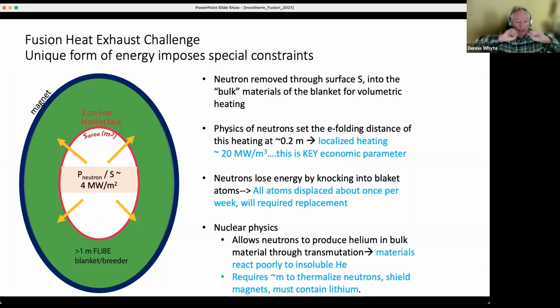So the neutrons basically stream out essentially isotropically out into some large thing. The neutrons move through that surface area S into this bulk. And the physics of neutrons, because they have no charge, set the e-folding distance of this heating at approximately 0.2 meters. It's not exact, but it's close enough. So what this immediately tells you is that you get a localized heating of around 20 megawatts per cubic meter, somewhere out in this medium that's stopping the neutrons through collisions. And this is the key economic parameter, the volumetric heating caused by the neutrons, which are 80% of fusion energy. And why is that?